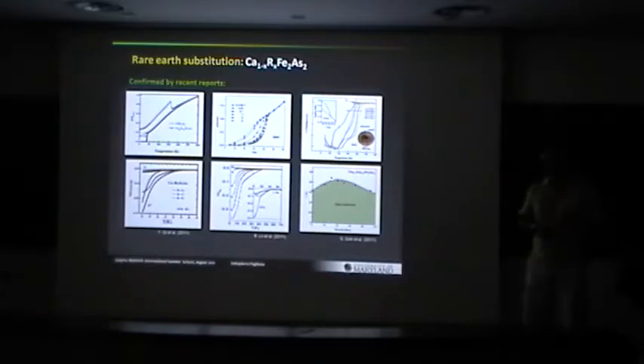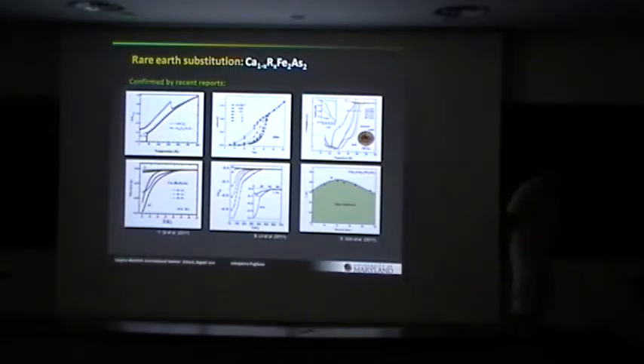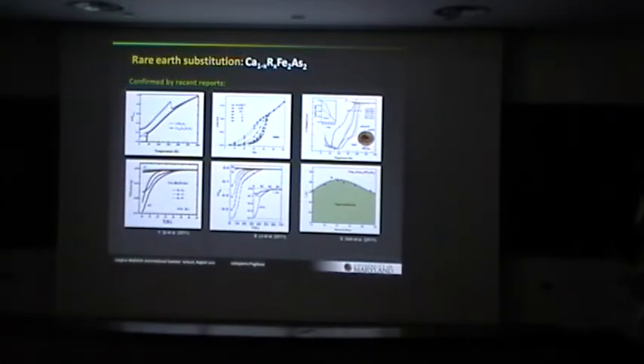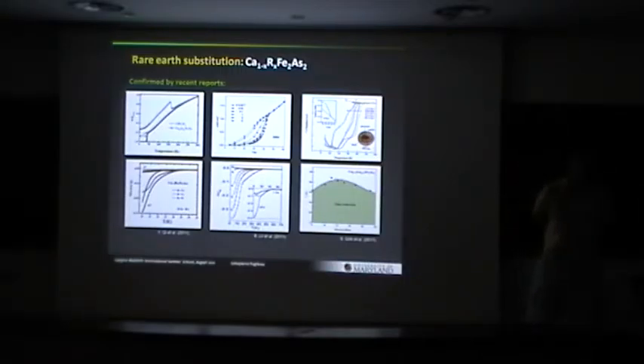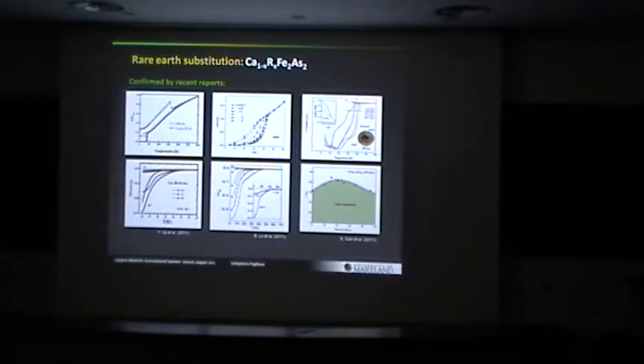So is that strain-induced superconductivity bulk or on the surface? Actually, there's evidence for bulk superconductivity. There's NMR data, and there's even specific heat under pressure, which seems to show that the 10 Kelvin phase has some bulk behavior, or bulk properties. From NMR, can you deduce what kind of pairing symmetry? Yeah, in theory you can. But this is NMR under pressure. You mean singlet or triplet? I'm not aware that they, well, they must have shown some Knight shift, but I don't know how the temperature dependence is. I don't remember off the top of my head.